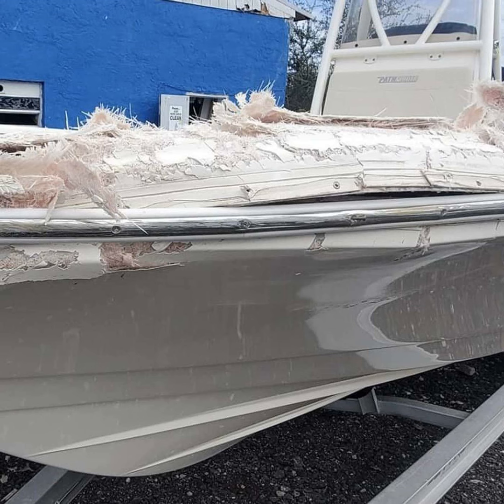When you're grinding around a fiberglass repair, we call that beveling the fiberglass. And what you're doing when you're doing that is you're exposing new fiberglass to bond to, and because you're essentially making a sloped edge that leads downwards into the center of the repair, you're expanding the surface area that you have to bond your new fiberglass to. So when you're doing a bevel, you want to use the guideline of a 12-to-1 ratio outwards.